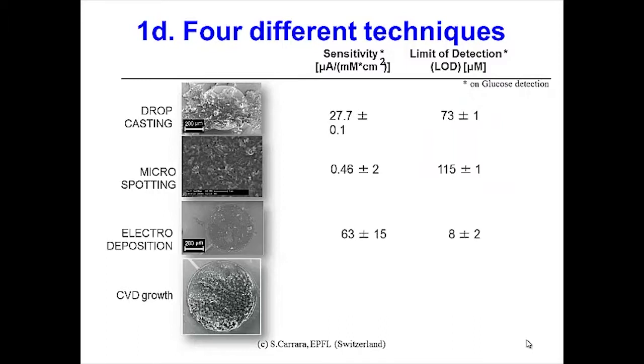What about electrodeposition? The sensitivity goes up again, so this is good news, but the best was obtained with the chemical vapor deposition growth. The main reason is that in this case we have no polymers, so all the surface of our carbon nanotube is available, and more, we have the carbon nanotube intimately electrically connected with our substrate, with our metals. So we also have a better electron transfer from the electrode to the carbon nanotubes. The best of the best we obtained on the uric acid, where we got almost, you see, 4-5 orders of magnitude more than the case of micro-spotting. But don't forget that we have changed the molecule, and of course changing the molecule changes the comparison.